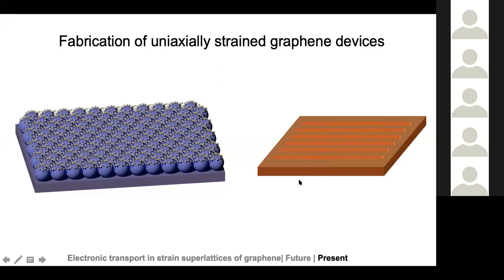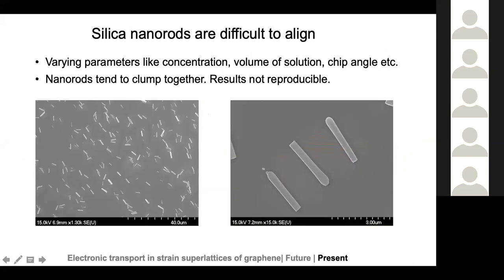will lie flat along the length of these rods, but in the transverse direction, it will experience periodic strain modulations. So if we look at the resistance in the transverse direction and in the longitudinal direction, they're expected to be different from each other. And that's what we're trying to see. First we thought, okay, let's use nanorods. They're the 1D equivalent of nanospheres. And we used nanorod solutions. However, as you can see from the scanning electron microscope images, the results aren't really good. In some cases, you'll have nanorods which are aligned parallel to each other, but for most of them, they just end up in random orientations, and you really have no control over the alignment. So we thought we'd move on to electron beam lithography.